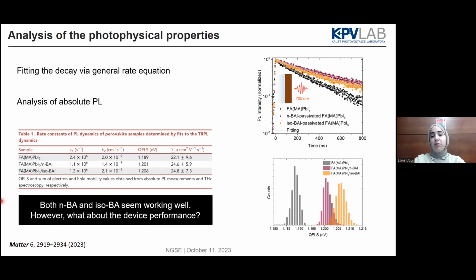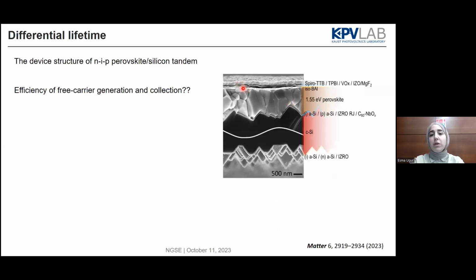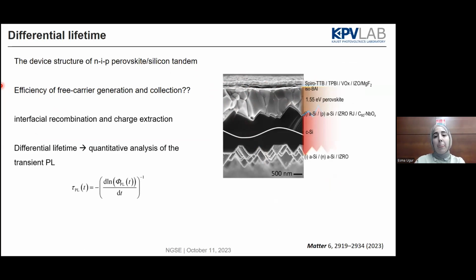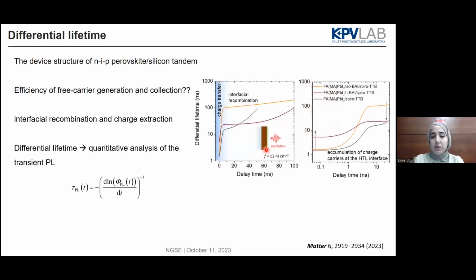But what about the device performance? N-butylammonium is a slightly longer chain than isobutylammonium. To understand this, we now need to see the charge extraction or the interfacial recombination at the perovskite and HTL interface, since we are using the NIP perovskite-silicon tandem structure that you can see. Now the perovskite is contacting with the spiro-TTB. So how can we check, after the generation of the free carriers, how the collection at that interface will be? To do this, we basically use transient photoluminescence measurement with the HTL stack,